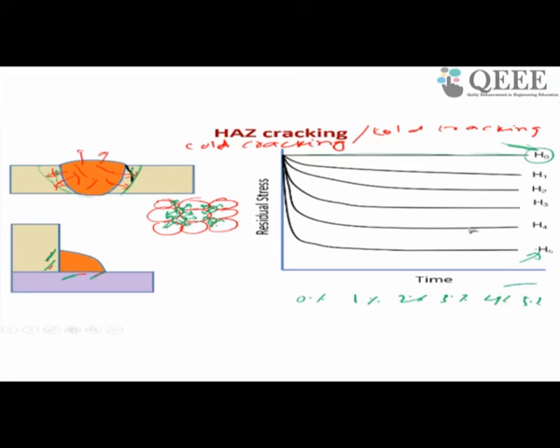Keep it for 1 year, 2 years or anything, hydrogen cold cracking will not occur at all. When you have hydrogen percentage 1%, 2%, 3%, 4%, 5%, and if you have more percentage of hydrogen, then with the presence of residual stress, it will happen; the crack will initiate very soon and it will propagate. As hydrogen percentage becomes less and less, it takes more time for this to form. So initiation time increases.